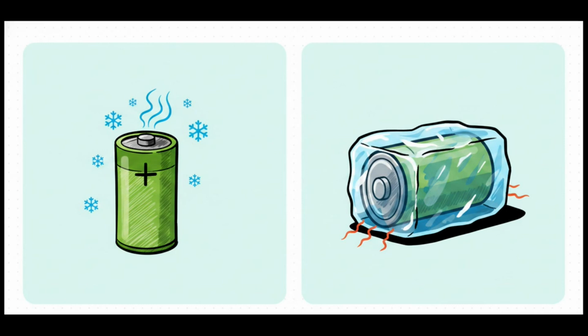Studies show that LFP charge transfer resistance is a whopping 3 times higher at -20 degrees Celsius compared to room temp. Plus, because LFP has a lower overall energy density, it actually has the highest thermal mass per energy charged. Simply put, it is way harder and takes a lot more energy to warm up a heavy LFP pack.